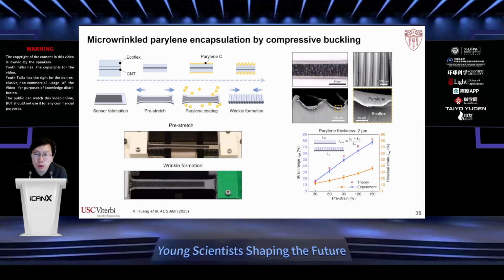So we basically use mechanical buckling again to introduce micro wrinkles into the parylene layer. So we pre-stretch. In this example, we show this stretchable encapsulation using a simple parallel plate capacitor strain sensor. Essentially, we use carbon nanotube as stretchable electrodes, and we pre-stretch the entire stretchable strain sensor, and then we coat it with parylene using a conformal CVD process. And then when we release the sensor, the parylene layer will buckle into microscale wrinkles due to compressive buckling.